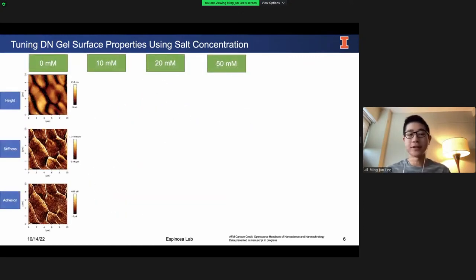So as this cantilever travels along the hydrogel surface, the laser spot keeps moving, and that gives us our signal. In the following slides, I'll be showing you quantitative imaging, or QI images. This is a special mode from JPK that allows me to extract three data channels simultaneously: the height, stiffness, and adhesion of my hydrogel surfaces.